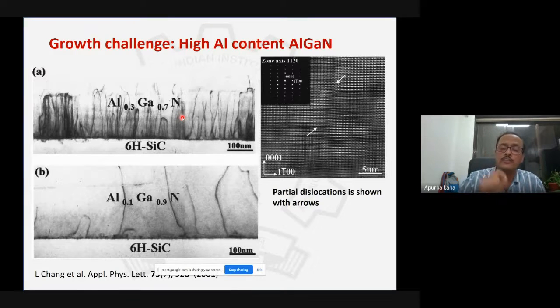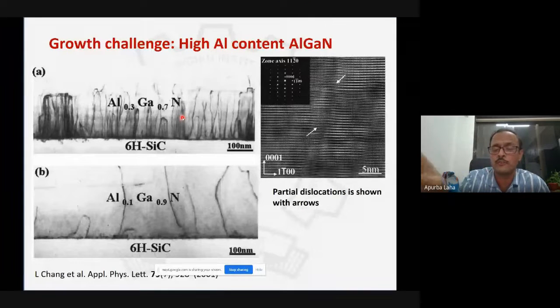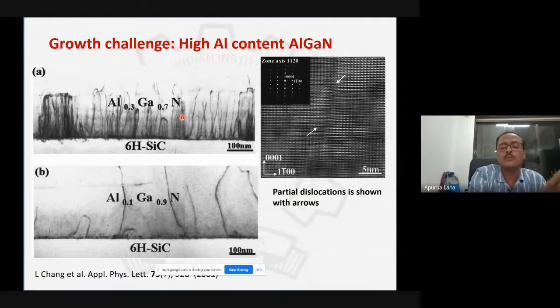That's because, as I said, thermodynamically, these materials need to be grown in a situation which is far away from thermodynamic equilibrium. So you have very little control on the structure quality if you are not in the proper regime. There are a lot of extended defects which come all the way from the interface to the surface, for example. That makes the devices much less efficient in terms of the optical light emission.